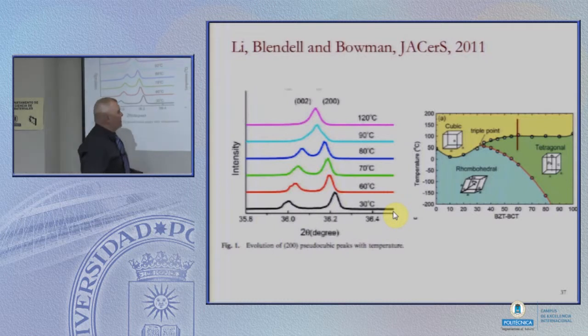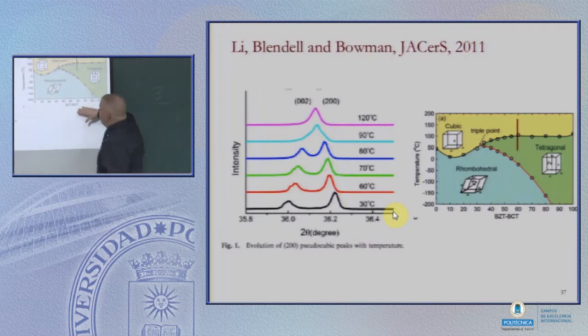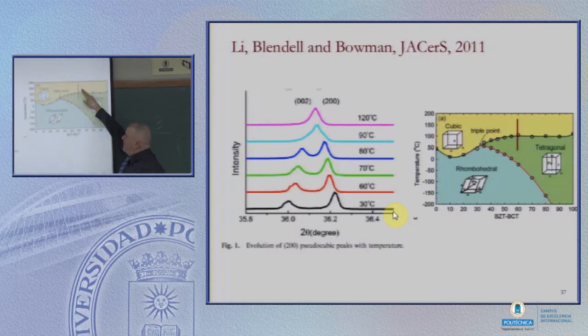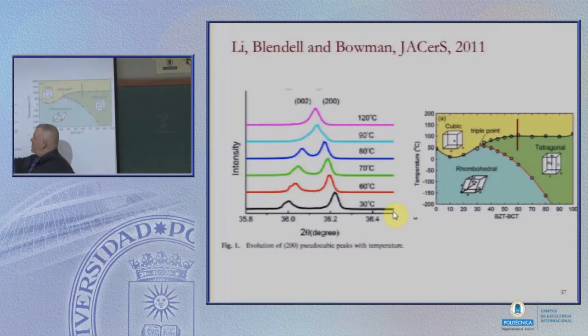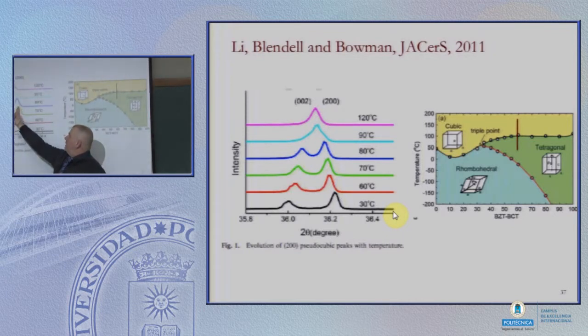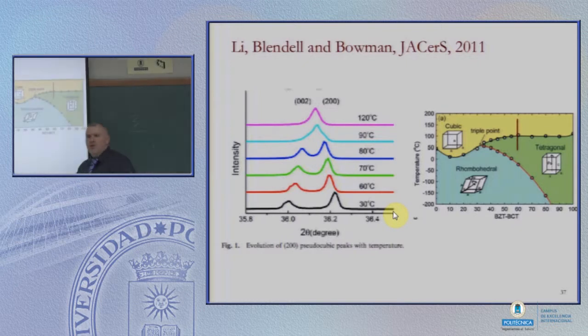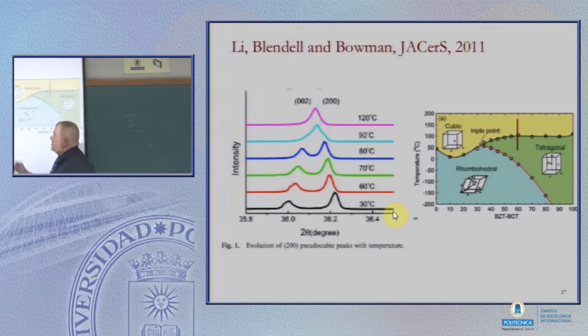And so this is a set of explorations for a particular composition. And we explored what happens with temperature. So you can see that it's very tetragonal at 30 C, and it becomes less and less tetragonal as we go up in temperature. But this is a very strong change, right? This is a relatively small temperature change. It's a very strong change in terms of lattice parameters. So it actually changes quite substantially. These are small dimensions, but it changes substantially. And then above 90 C, it looks essentially cubic. 120 C looks essentially cubic.